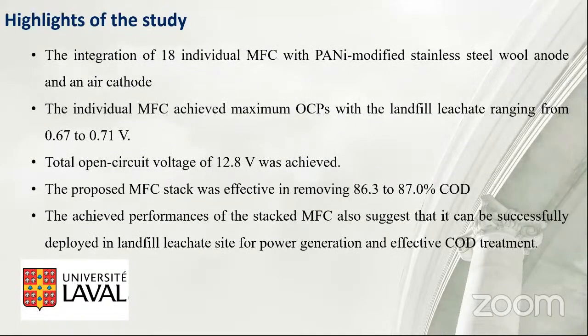The highlight of the study was basically the integration of 18 individual microbial fuel cells with polyaniline modified stainless steel anode and air cathode. The individual microbial fuel cell achieved maximum open circuit potential with the landfill leachate ranging from 0.67 to 0.710 volt, and the total open circuit voltage we could attain was 12.8 volt. The proposed stack of MFC was effective in removing 86 to 87% chemical oxygen demand. The achieved performance of the stack MFC also suggests that it can be successfully deployed in landfill leachate sites for power generation and effective COD treatment.